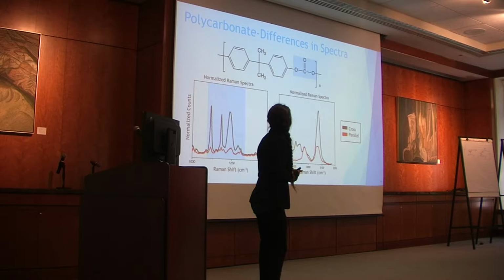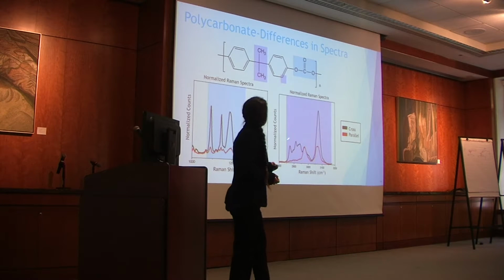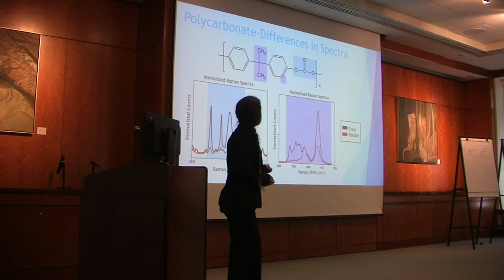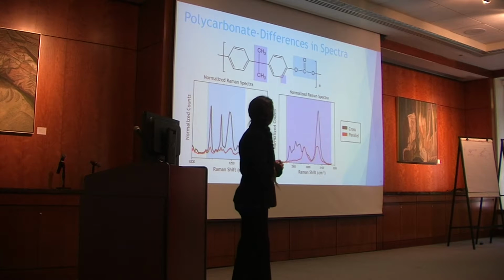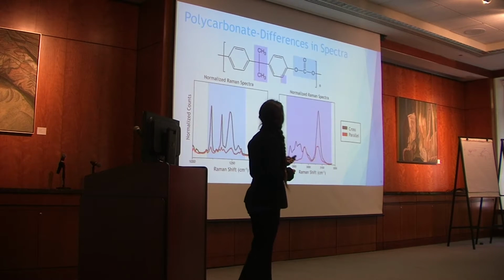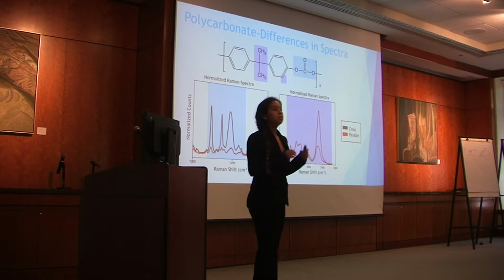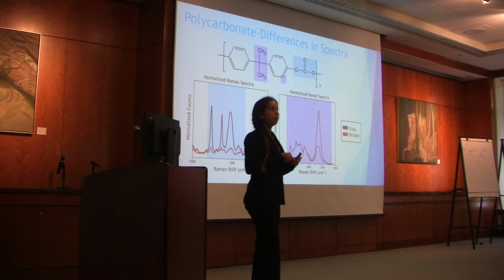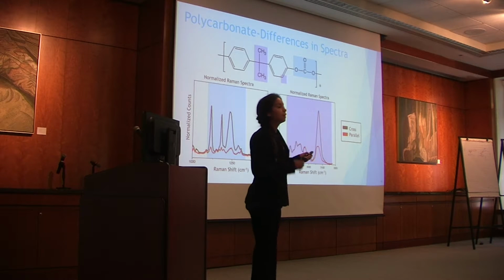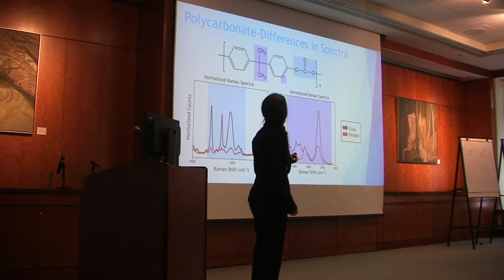We then looked at differences in the spectra. As you can see, there are very substantial intensity differences when looking at cross versus parallel. So this was just adding to the story that parallel polarized Raman can help in understanding the molecular alignment of this polymer.